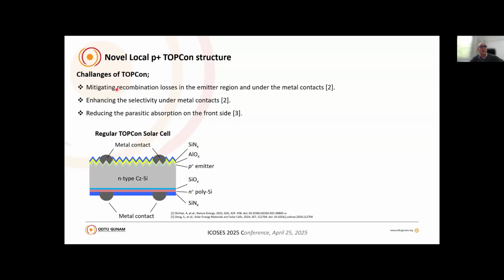Well, local TOPCon is an idea to reduce the recombination losses on the front side. The backside is the same as the standard TOPCon solar cell, but on the front side we have another TOPCon structure under the metal layer, while outside the metal layer we do not have any heavy doping. So the emitter is lightly doped, but the region under the metal layer is passivated by using a poly layer, and then we have very low front side absorption. So this is the idea.